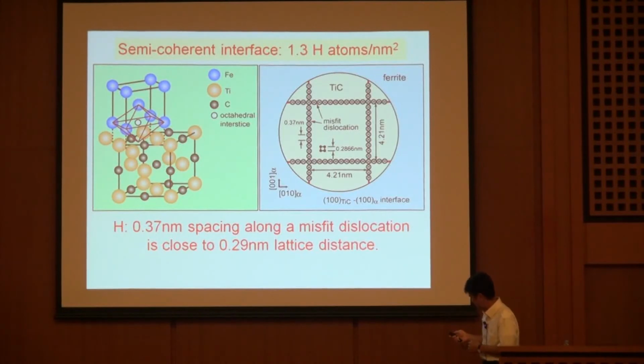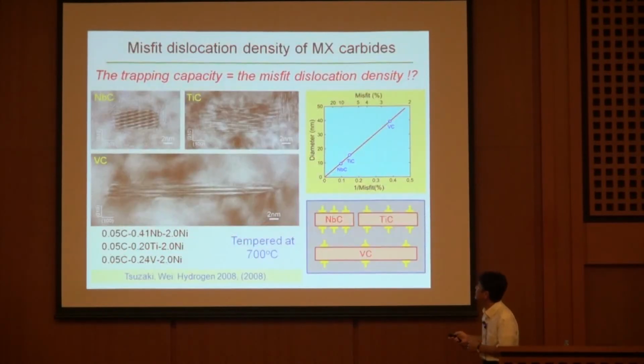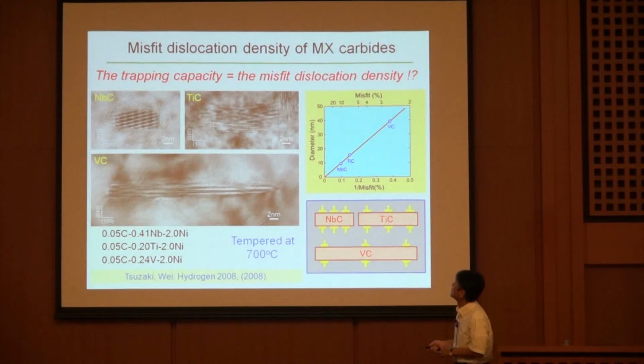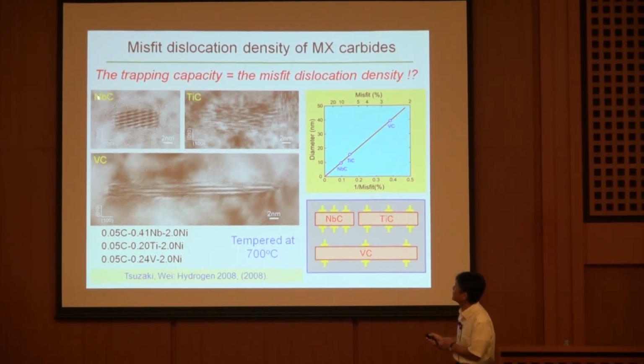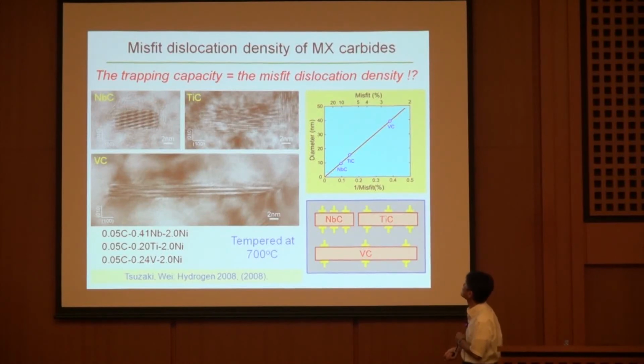So then we considered further. Trapping capacity would be related to the misfit dislocation density. This is a microstructure feature of three kinds of steel with different niobium carbide, titanium carbide, and vanadium carbide at the given temperature condition like this. So you can see the different kinds of morphology.